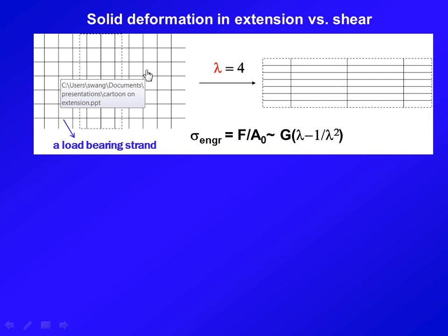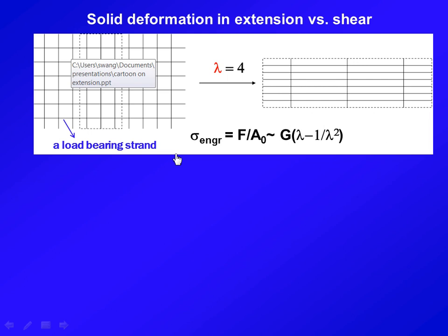So if you have 6 load-bearing strands in the tensile direction, if I quadrupled my length without reaching the force imbalance point, without reaching enough tension in the chain for the chain sliding to take place yet, then I should still have 6 strands bearing load.